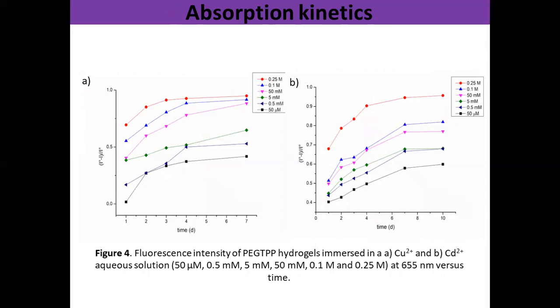The absorption kinetics of the PEG-TPP hydrogel was investigated from 50 micromolar to 0.25 molar copper 2+ and cadmium 2+ aqueous solutions, as figure 4 shows. The PEG-TPP hydrogel immersed in a copper 2+ aqueous solution reached the absorption equilibrium after 5 days. Meanwhile, the PEG-TPP hydrogel immersed in a cadmium 2+ aqueous solution reached the absorption equilibrium after 7 days. However, the response to the naked eye can be seen after a few hours of starting the experiment.